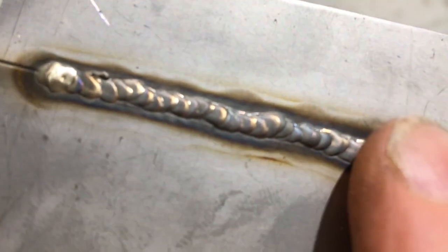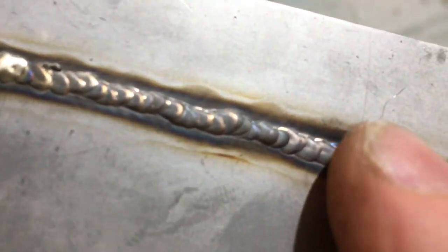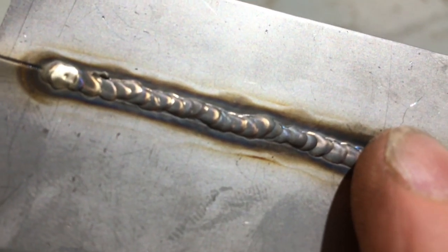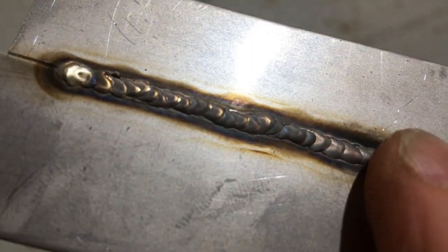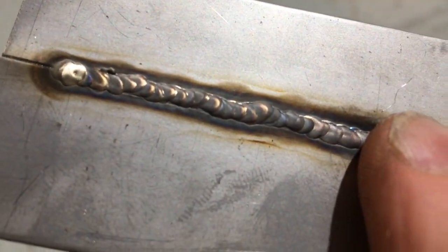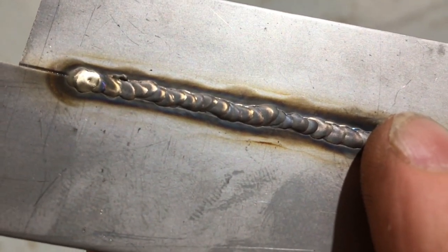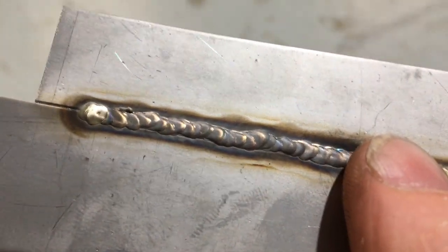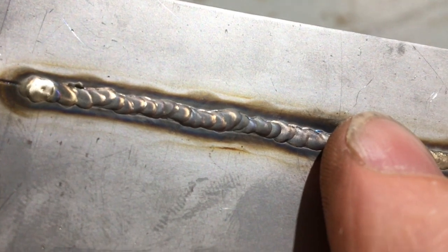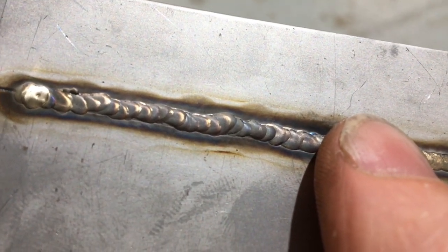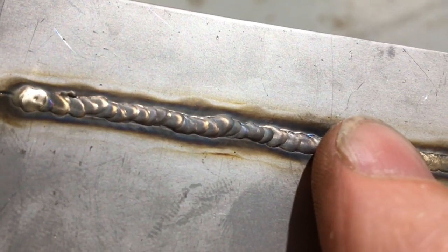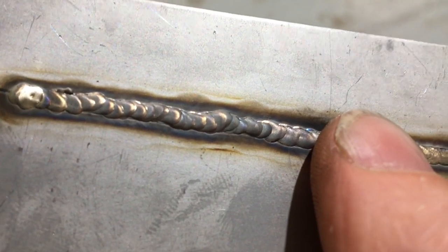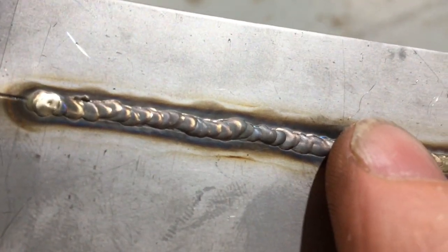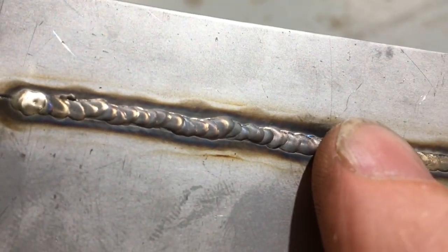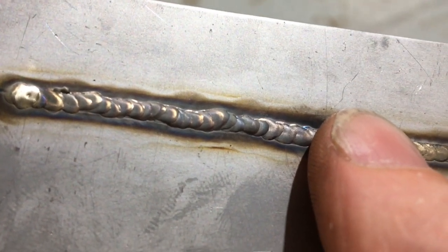And this is the one where all we did was cut down the amperage, which restricted our travel speed, and what we've actually got is more heat input, a wider heat affected zone, and a weld which is starting to turn grey, which is a sign of overheating on stainless. Also the gas coverage may be lacking slightly. Now sometimes on plain carbon and alloy steels it's desirable to move a bit slowly to let the heat build up in the part to avoid quenching and cracking.